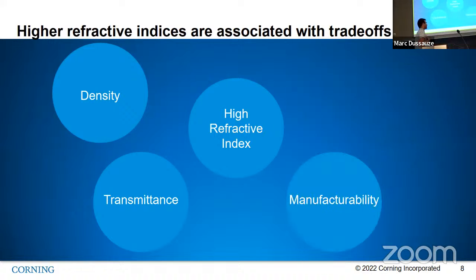Manufacturability, that's for us in the plant. So we need the glass to still be manufacturable. As we increase refractive index, typically the glasses become less and less stable, which is quite difficult for us when we need to produce them in high volume. They tend to devitrify, basically. And also they are very fluid, which makes it more difficult for us to cast them properly.